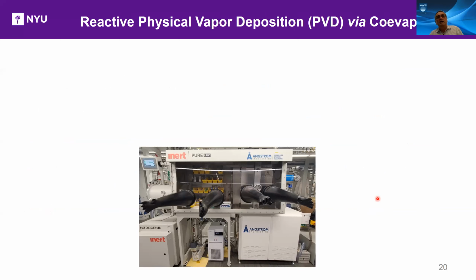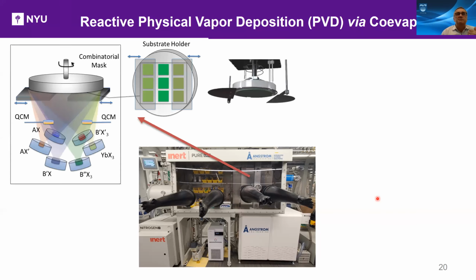So we do what I am calling reactive physical vapor deposition, because this is not the old physical vapor deposition where you have just metals and atoms evaporated and then condensing on the substrate. We evaporate precursors that, upon landing on the substrate and condensing, actually also react. And that reaction depends on substrate temperature and things like this. So I'm calling it reactive physical vapor deposition.